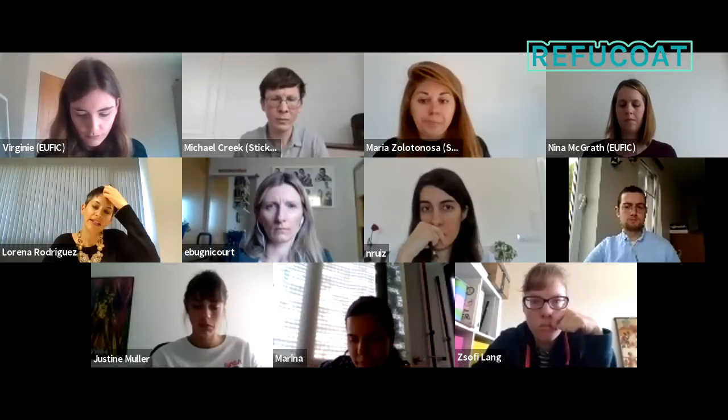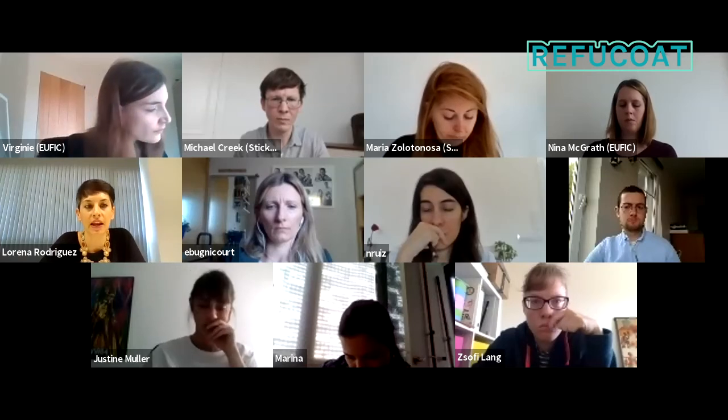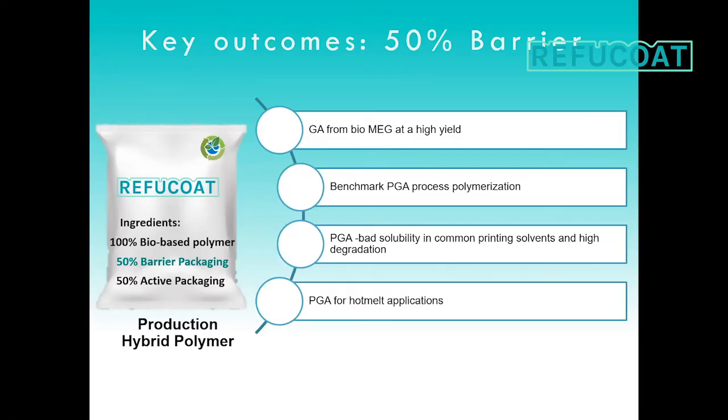Okay, one of the problems with the PGA is not about its production, but that it's a material that is very sensitive to oxygen. That means that it degrades in an oxygen atmosphere. And apart from that, it's very difficult to dissolve in common printing solvents. So that was also a difficulty that we found during the project execution, because the very beginning idea was to print the PGA coating using common printing technologies.